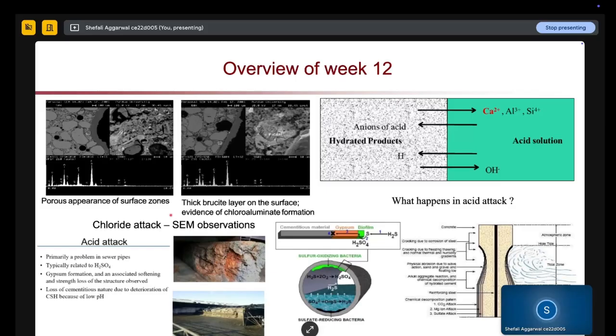The next type of durability problem is chloride attack. In chloride attack, if you see two types of materials here, in the first one your concrete has a porous appearance of the surface zone, which will promote the ingress of chlorides into your concrete system. And here there is more CSH forming, and your surface layer is much thicker, which will repel the entry of chlorides into your concrete system. This is checked using SEM analysis.